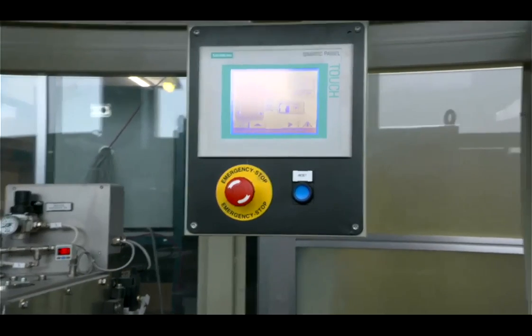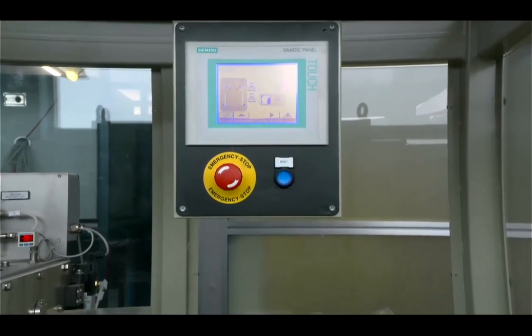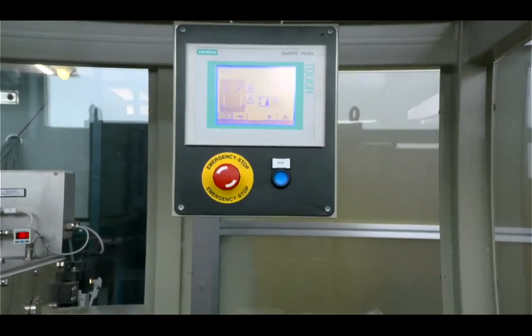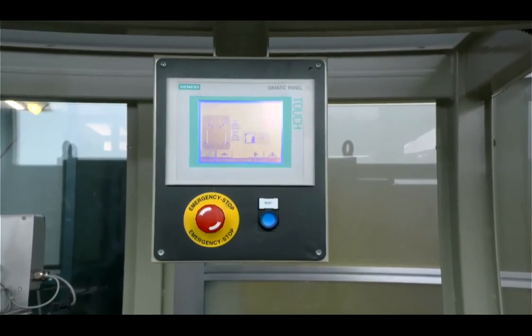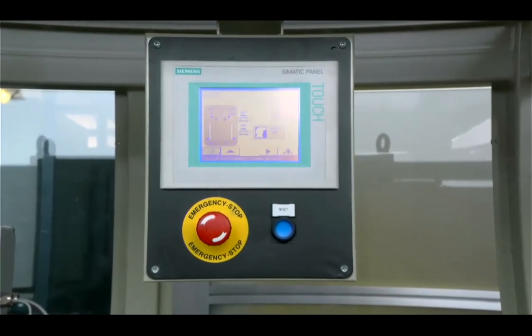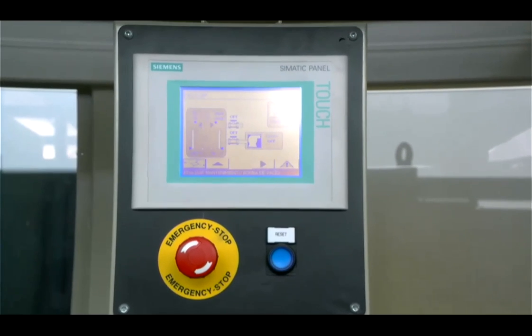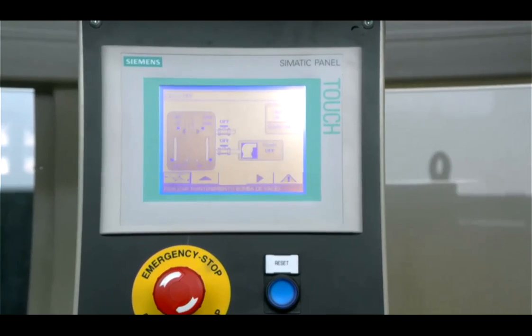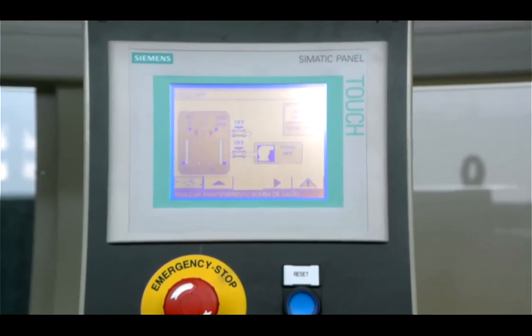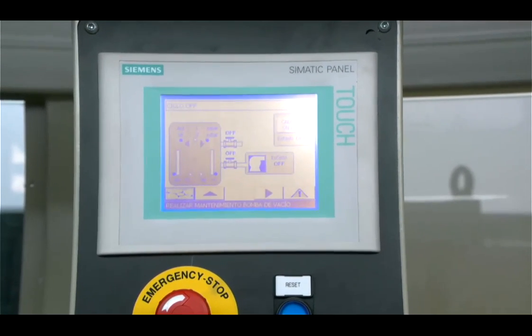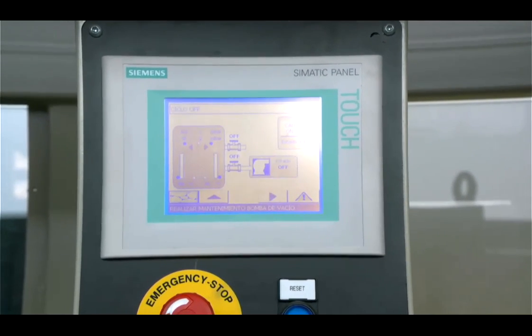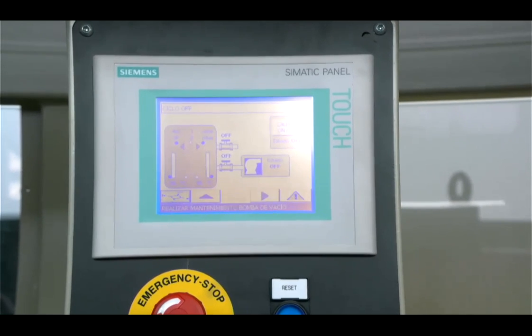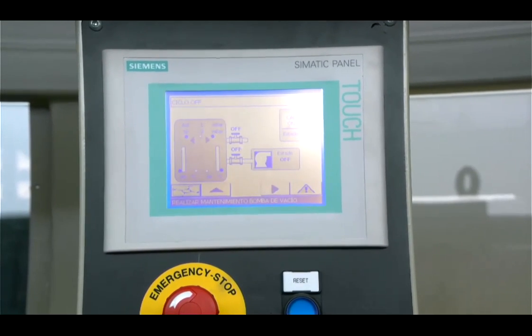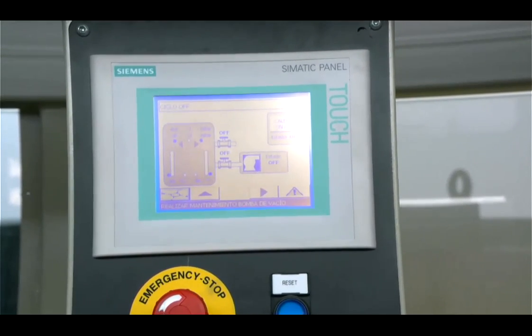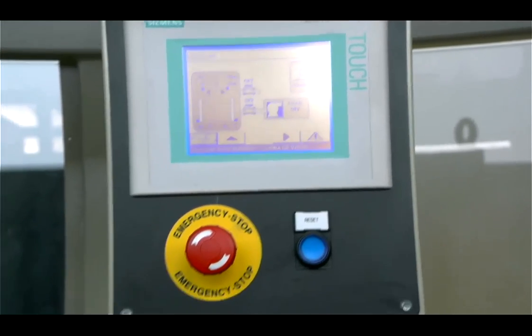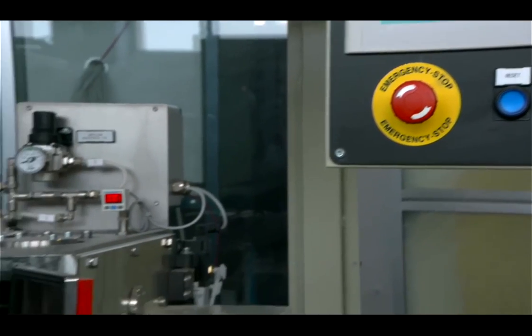So once we have done all the experiments with these cells, we have never faced problems. We have to say that all the cells that we are doing with lower capacities, because with this pouch cell size we are using for example 30 ampere hour cells, but for lower capacity cells, we are working in this dry room, and we are doing all the steps there. We didn't face any problem in the electrochemistry.